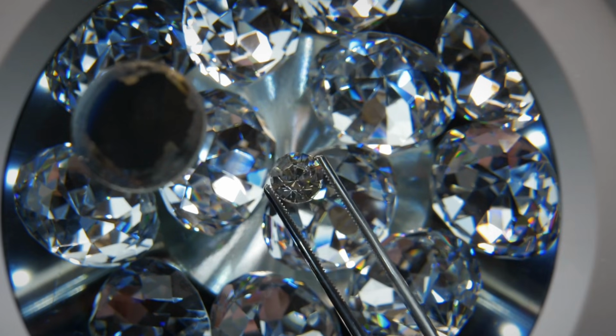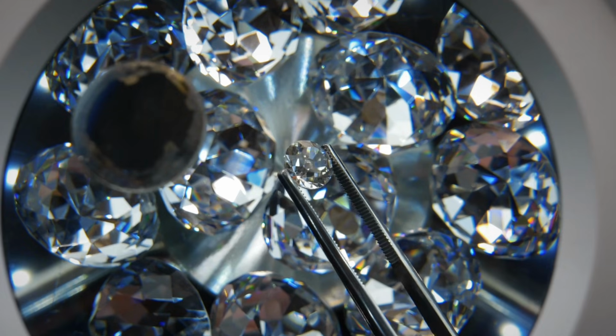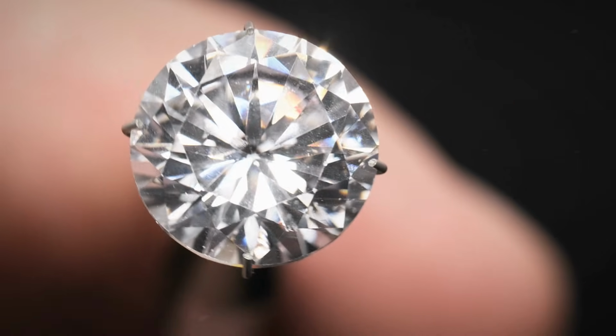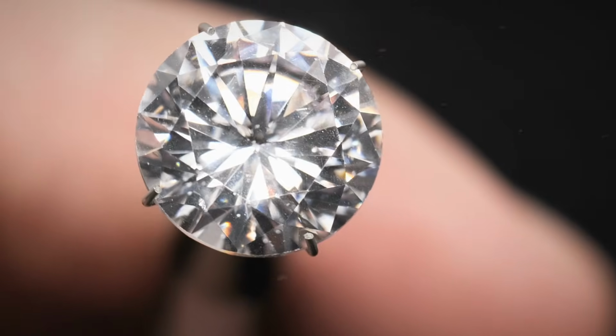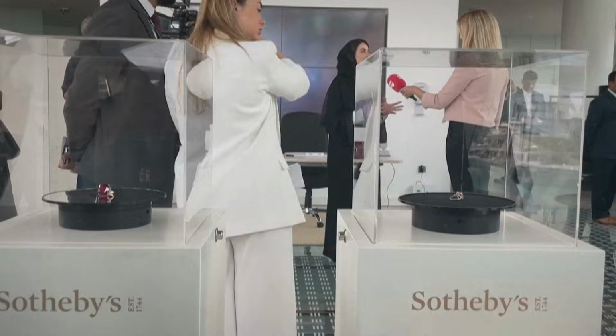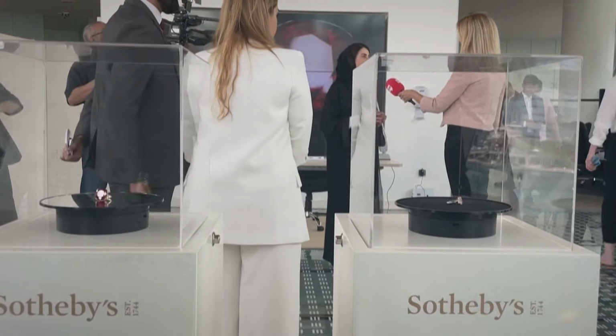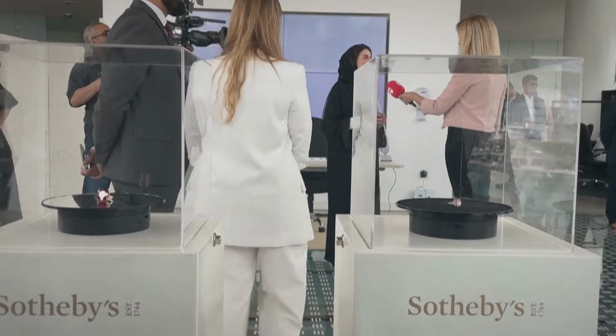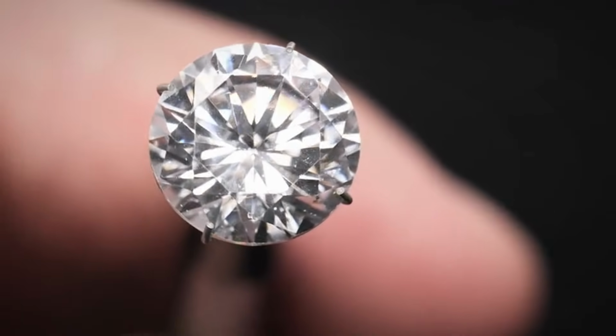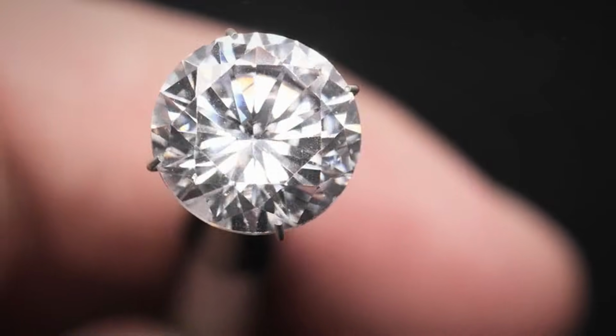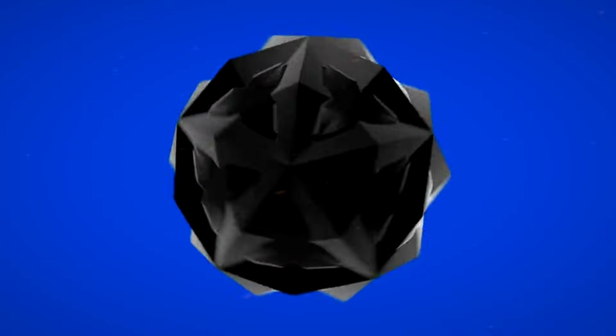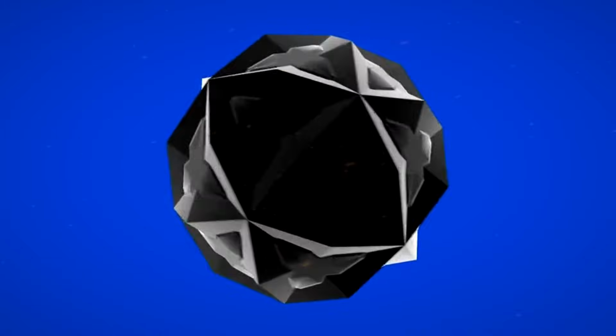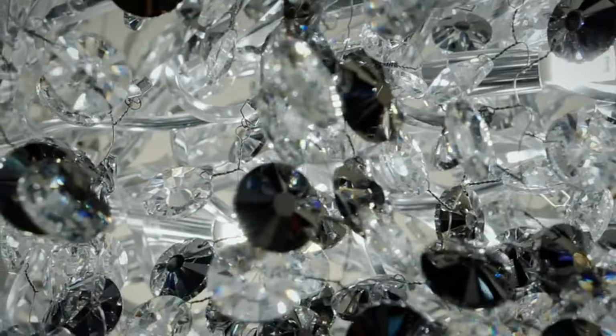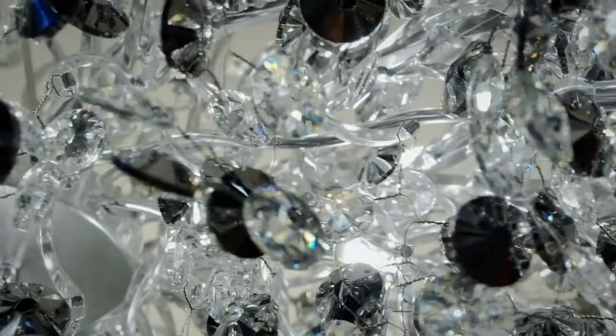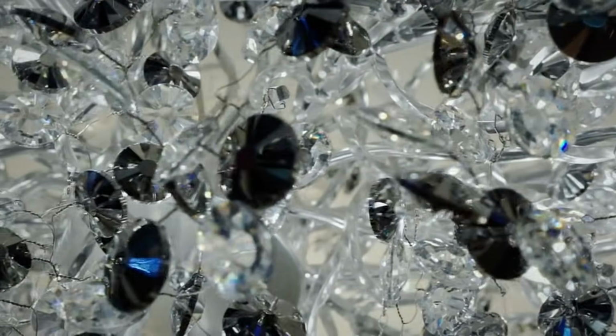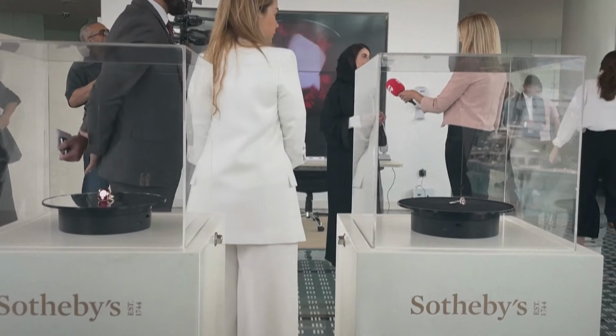The principle is simple. Electrical conductivity testers send a low-voltage current into the stone and measure how easily electrons flow through it. Moissanite, made of silicon carbide, permits current to pass. Diamond, composed of pure carbon in a tetrahedral lattice, is an electrical insulator. Even synthetic diamonds, unless doped with certain elements for industrial use, remain non-conductive. That means a stone that registers positive under thermal and conductive testing is almost certainly moissanite.